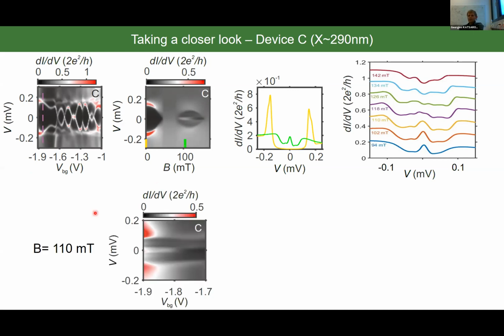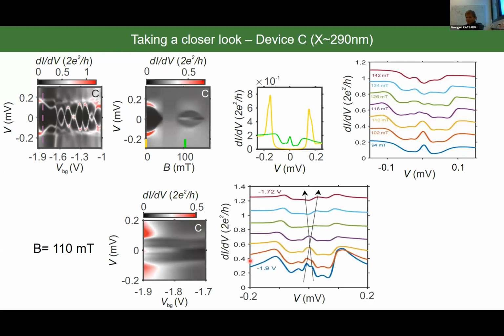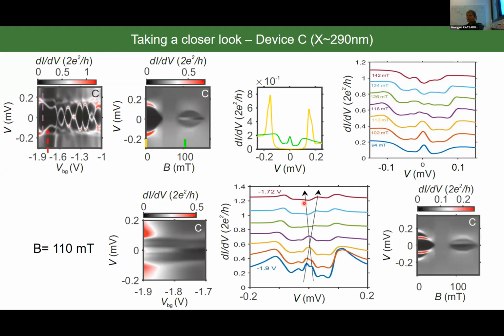If we now put a magnetic field of 110 millitesla, which is in the center of the first lobe, and measure again the differential conductance versus bias and gate voltage, you can see that the zero bias peak extends for actually a bit more than 100 millivolts. However, if you take a close look, you will see that very close here, there are two peaks which merge together and then separate again, telling you that this is also an Andreev bound state. As a verification, if you fix your gate voltage at minus 1.8, that is the plot you would get, so no zero bias peak.